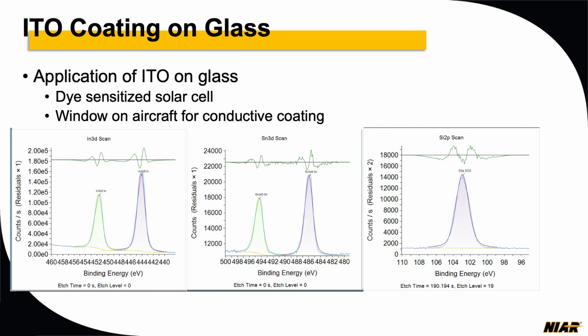Okay, the next sample is an indium tin oxide coating on a glass. The two applications that I'm familiar with are dye-sensitized solar cells, which I used for my master's, and that is one of the conductive coatings. The other application is for windows on an aircraft, for conductive coating. So when an aircraft has a static buildup, because of the conduction, it basically dissipates. So we were looking at the ratio of indium and tin, and there are different percentages for different windshields in the industry.